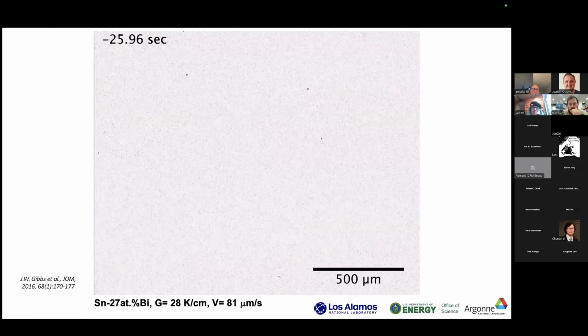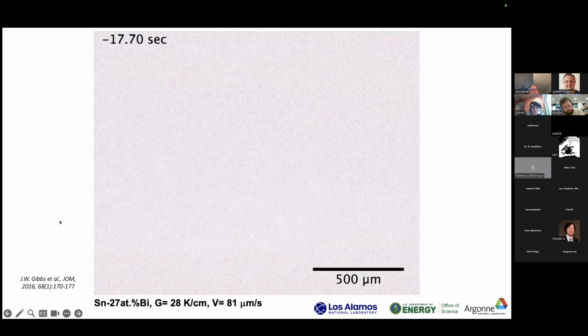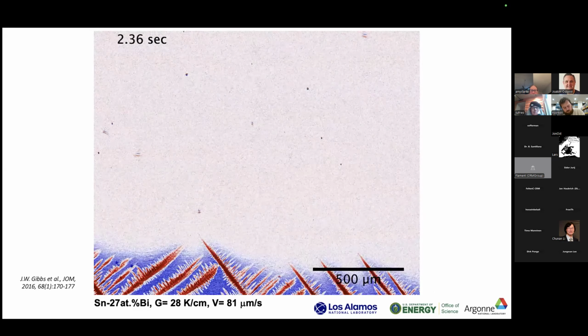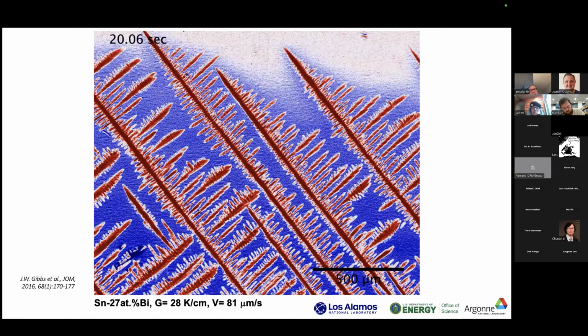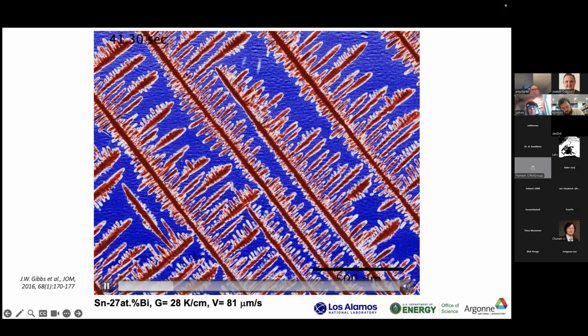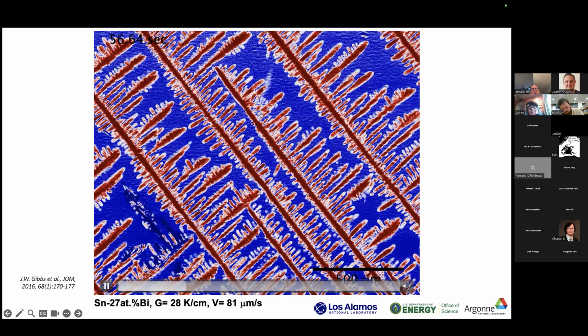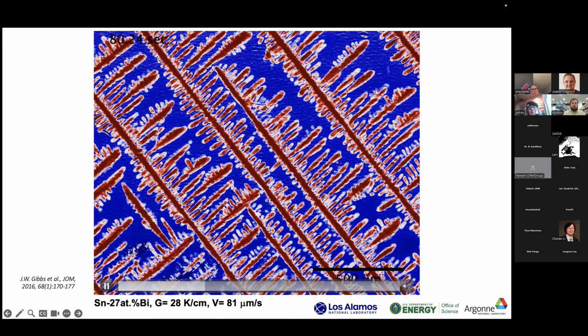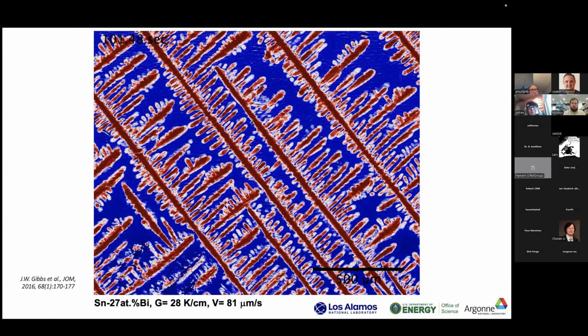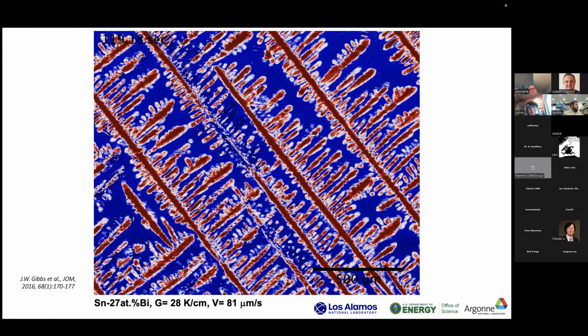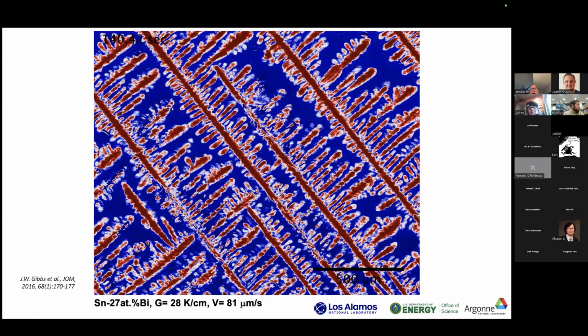And I do want to highlight that CET is important for additive manufacturing, but it's also important in conventional solidification processes as well. I had previously shown you this top-down directional solidification for tin bismuth. I'm going to now show you the bottom-up version. What you'll see in this case is the dendrites growing bottom up, I think colored red, and then you see the blue bismuth solute settling. Again, it's higher density. And then you can see the fragmentation of these tin-rich dendrite arms off into the melt. Again, they're more buoyant, they want to float. And those kinds of events can actually trigger columnar to equiax transition, for example, within a casting. So it's also important to metal casting as well.